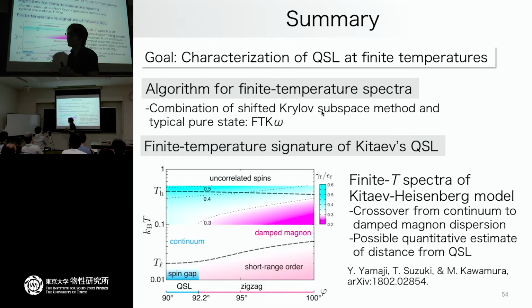Sorry, not Nasu, but Yoshitake-san in Professor Motome's group already checked the finite temperature behavior at this limit, and it is already confirmed that this ratio cannot be smaller than 0.3 in this range. However, below this temperature scale, we have no reliable method so far. So I just stop here because this temperature scale is quite safe.